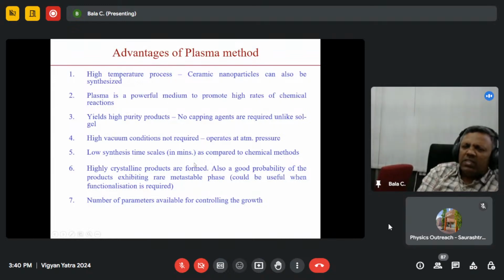The other important thing is, since it's high temperature, you will get highly crystalline products, unlike amorphous products, which have very different kinds of applications. Also, you have a very high temperature at the core, and within a few hundred microns you have a very low temperature. There's a sudden thermal quenching, a sudden fall of temperature. That gives you thermal stress in the system. Your nanoparticles have some amount of thermal stress, which can give rise to dangling bonds, or can be used for functionalization and many other applications. So this is one of the advantages. Maybe not all, but quite a number of them you can use this property for some applications.